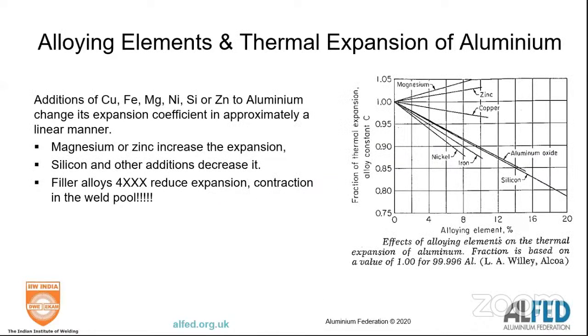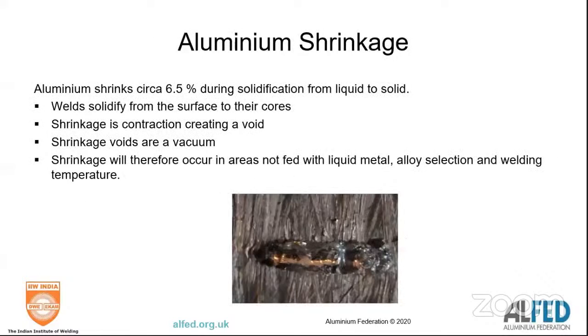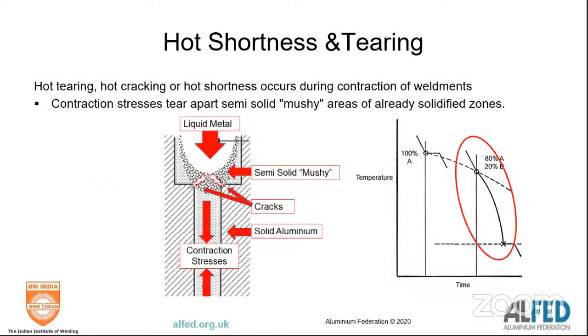And unusually with aluminium, some alloying elements, particularly the silicon elements, which we put into 4000, actually reduce expansion. So with 4000 series aluminium, what you could end up with is a weld that, as it heats up, is actually contracting, whereas the parent metal will be expanding. So you have contraction and thermal expansion issues. Very, very roughly, if you work on the basis of a 6.5% shrinkage from liquid to solid, that gives you an idea of what's going on in an aluminium fusion weld. What will happen is that manifests itself as hot tearing or hot cracking within the areas of weldments, particularly with alloys that have very large solidification zones.